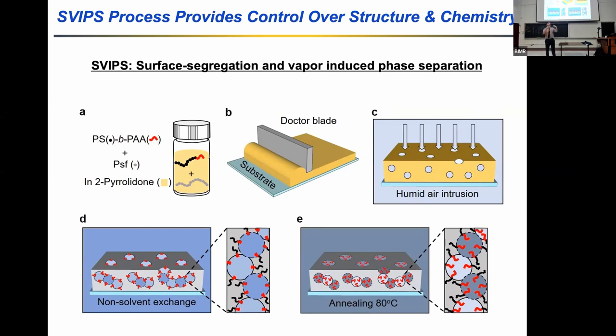But then we're going to go ahead and precipitate it using a humid environment rather than plunging it into a non-solvent bath. And the reason for that is that the exchange of water vapor and solvent is much slower, leading to a slower precipitation and a lacy, spongy-like structure, rather than just plunging it into a water bath where I have very rapid solvent-non-solvent exchange.